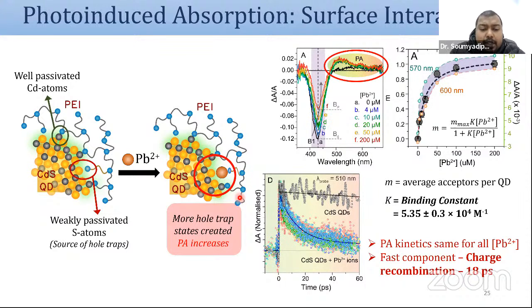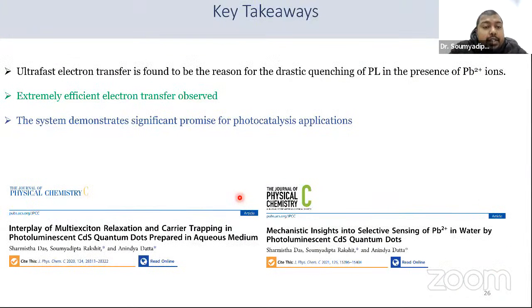then this trap state is created, and the recombination of the excited electron and the hole is hampered, and therefore there is a charge separation, and the photoluminescence is quenched rapidly, and the ultrafast electron transfer happens around 6.2 picosecond or so. So in conclusion, the ultrafast electron transfer is found to be the reason for the drastic quenching of the PL in the presence of lead-2 plus ions, and extremely efficient electron transfer.